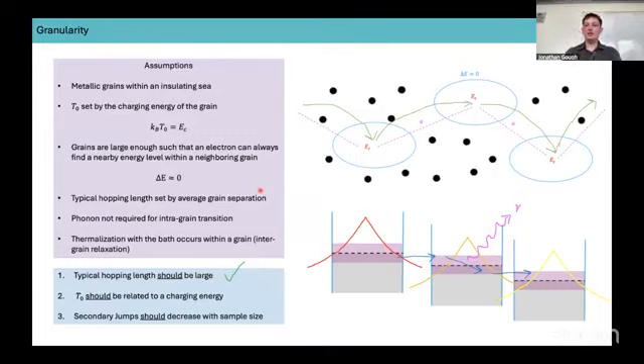So the typical hopping length here would be given by the average grain separation, which obviously has to be comparable or larger than the grain size. So it should be quite large. Phonons should be weakly involved in the transport between grains because these energy levels are so nearby in energy. However, relaxation occurs within the grain. So you get the separation between transport and relaxation, hence why we would observe this weak electron-phonon coupling.